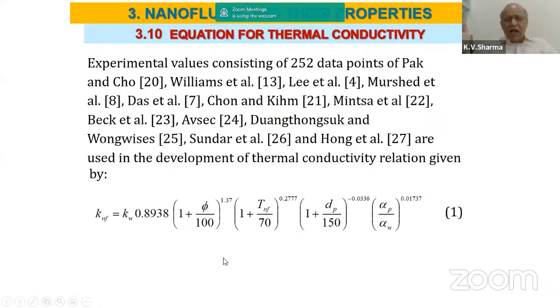So I have taken a large amount of data which has been presented by various authors working with different materials, different particle sizes, different operating temperatures, different concentrations. So I can vary the concentration, I can vary the temperature, I can vary the particle size, I can vary the material. So there are 4 parameters involved when we try to determine the thermal conductivity, as shown in this equation: concentration, temperature of the fluid, particle size, and material. As concentration increases, thermal conductivity increases. As temperature increases, thermal conductivity increases. As particle size increases, thermal conductivity decreases.